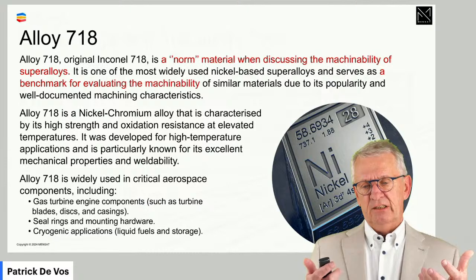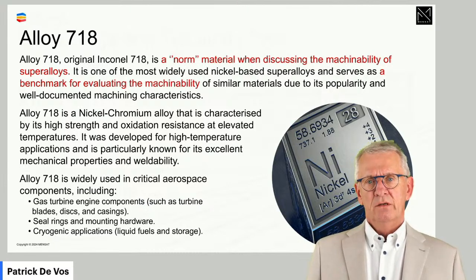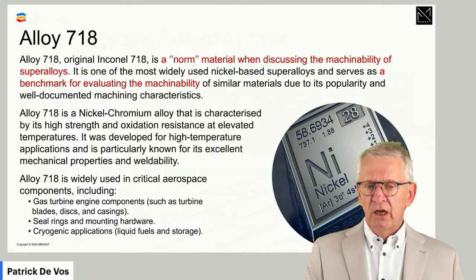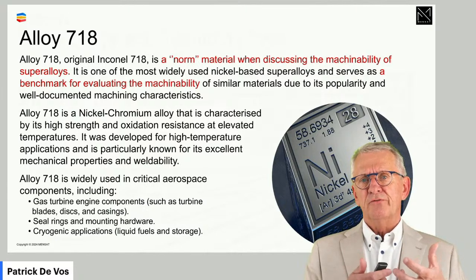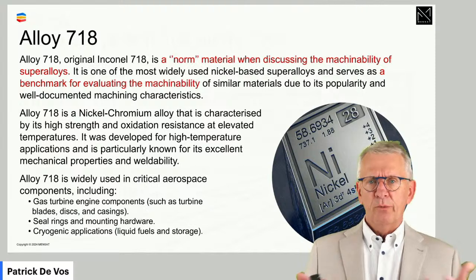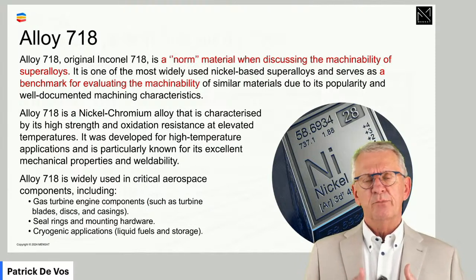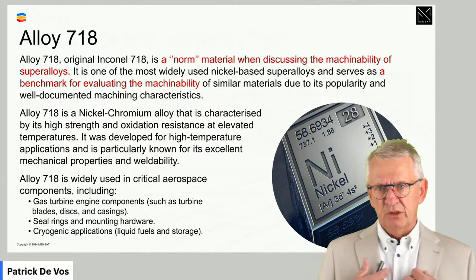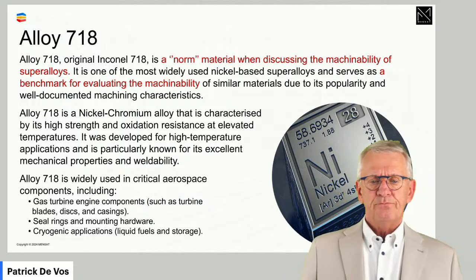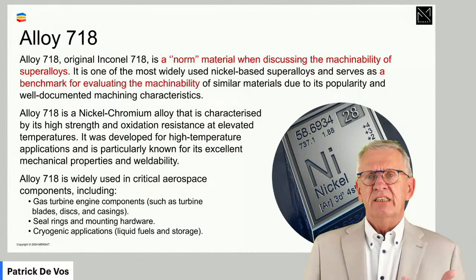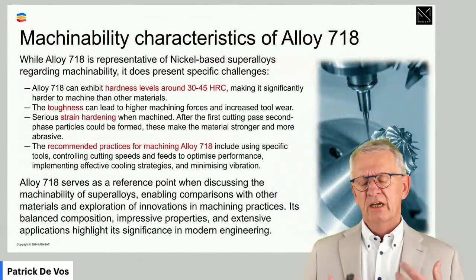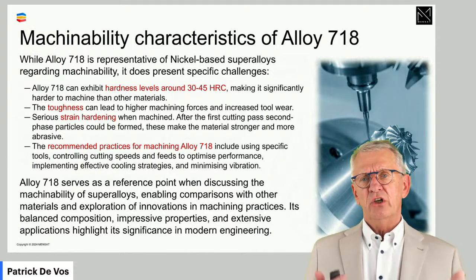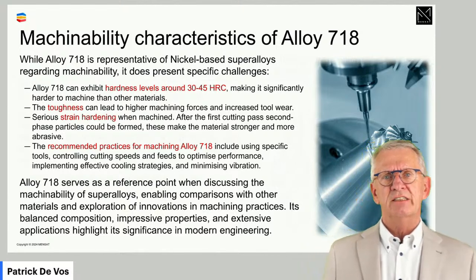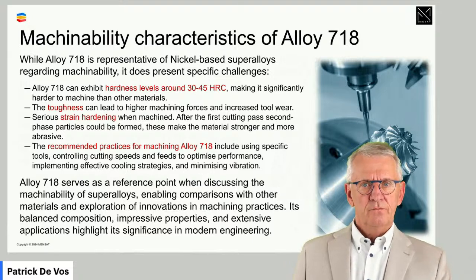If a material is allowed to be labeled alloy 718, and the origin of it is Inconel 718, it has a number of standardized norms, properties, features about composition, about properties, about also, from our perspective, machining people, machinability elements. Alloy 718 shortly is the reference material we use more and more when we talk about machinability of superalloys. Now, just so that you have an idea, what is alloy 718? It's a rather hard material, and depending on how it is produced and thermal treatments and so on, it's between 30 and 45 Rockwell C.